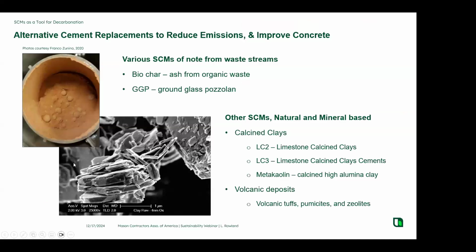Other supplementary cementitious materials that we're investigating are materials from waste streams, such as biochar, which is a specialized type of ash that's produced traditionally from agricultural applications. And then, of course, we can take waste glass, that recycled glass that we all put in our recycle container, which can be ground up very fine, and in special applications, when it's treated properly, can turn into a pozzolan. It can be a supplementary cementitious material. These materials and fly ash don't have the same replacement value as slag. One of the reasons slag is so good is it has a very high replacement level. These tend to be fairly low just because of what they are.